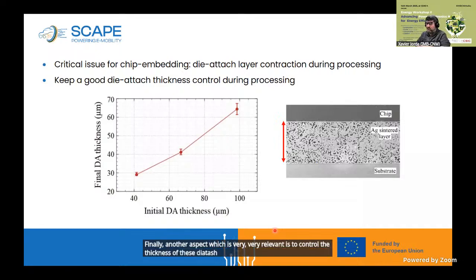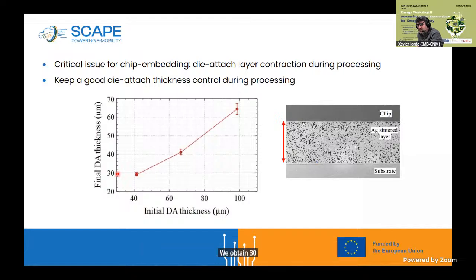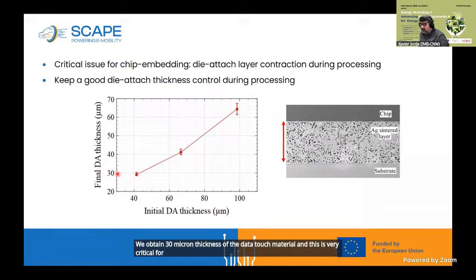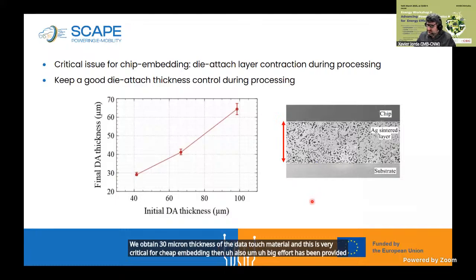during the process. When the silver die attach layer is processed, there is a contraction. For example, in this case, we start from around 40 microns thickness on the initial material, but at the end, we obtain 30 microns thickness of the die attach material, and this is very critical for chip embedding. Then also a big effort has been provided here to control these processes.